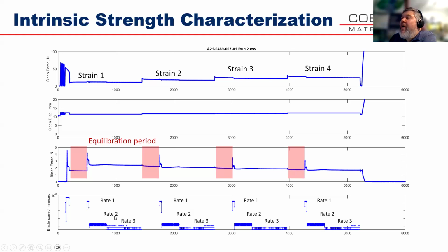In fact, the reason that we're cutting at different rates is that the threshold is going to be the energy input at basically the slowest possible rate, right? But since we can't really measure at a rate of 0, we measure at a couple of rates, and what we're hoping is that at the slow rates, that's close enough. And by measuring 3 rates, we're able to check how much dependence on rate the measurement has. If the measurement shows no rate dependence or very small rate dependence, then that tells us that we've succeeded in the measurement. If not, then we need to slow things down a little bit more.